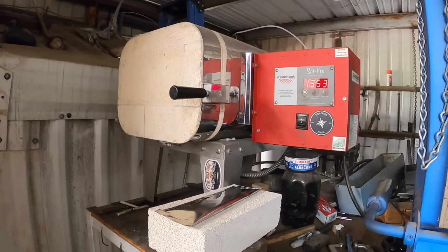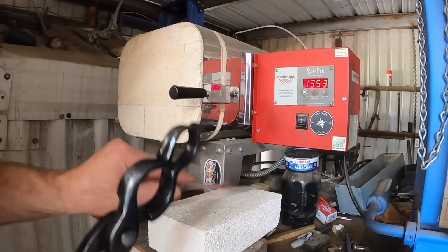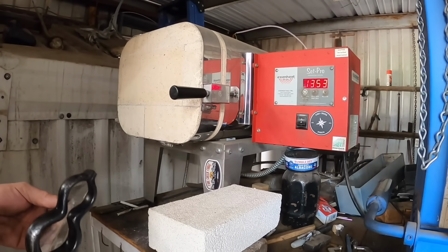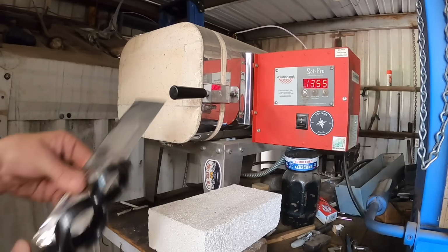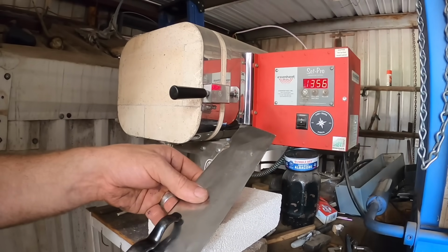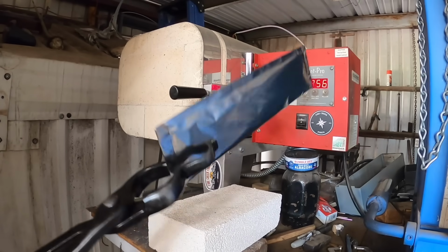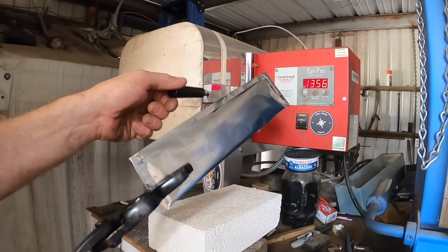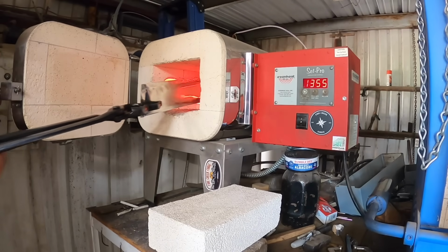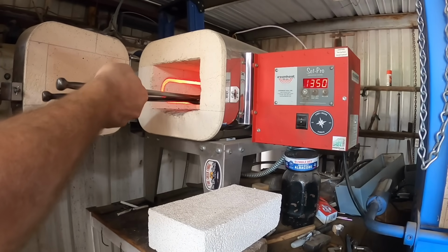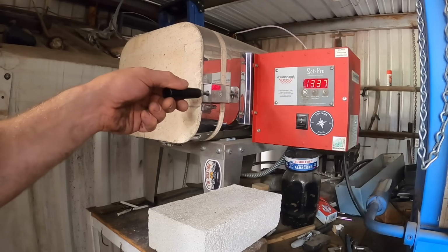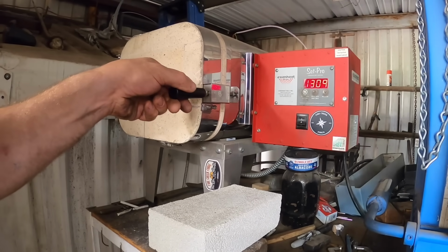All right, the next thing is to pop this into the kiln, where it's going to heat up to about 1560 Fahrenheit. It'll hold there for about 15 minutes and then move on to the austenitizing temperature of 2050 degrees for a pretty decent mid-range-ish heat treatment on this MagnaCut steel.